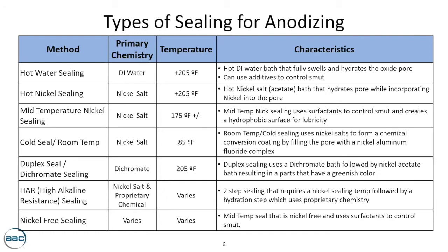Duplex seal and dichromate sealing. This is a pretty old type of seal that was used in the past, and what it involves is taking an anodized part, going into a dichromate bath, followed by a nickel acetate bath, and the result is a part that looks green. And when this seal was more commonly used, the quality of that seal was assessed on how green the part was. So a green part indicated a good seal. In the current environment, dichromate sealing isn't very popular. It's on a few specs, very rarely used. The most common type of sealing you're going to see is nickel sealing.